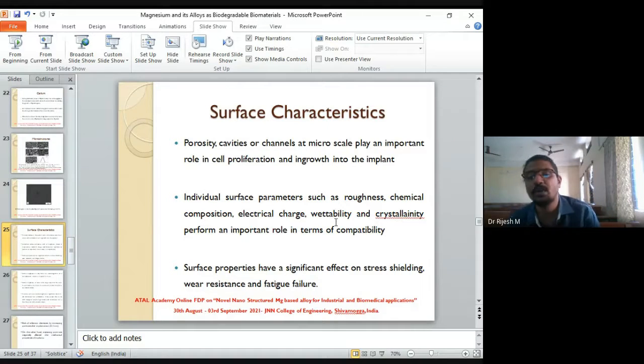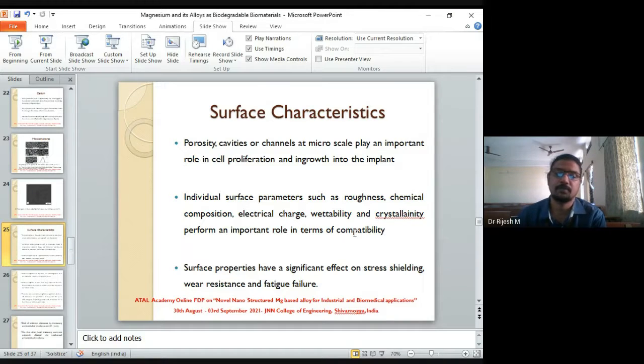So if you want to increase the wettability, one way to do it is to go for a coating which has good wettability. Otherwise, you'll have to change the implant material altogether. Crystallinity is important. They're all important before you go for biocompatibility. Surface properties have a significant effect on stress shielding. So if the surface roughness is very high, you may not have the stress shielding to a larger extent. Surface properties have too much to do with wear resistance and fatigue failures too.